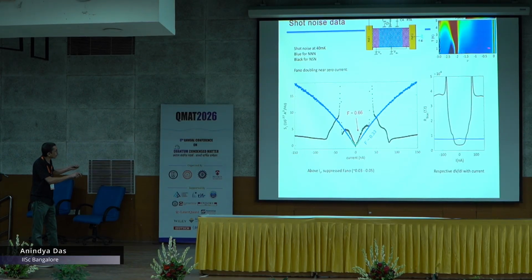So this is the Fermi liquid part. I am measuring the noise, and if you fit the data, the slope is 0.33, which is expected, actually 0.32 or 0.3. So that is like the classic Fermi liquid Fano factor you look at. Interestingly, now if you switch the system, these are normal, but make this the superconducting part.